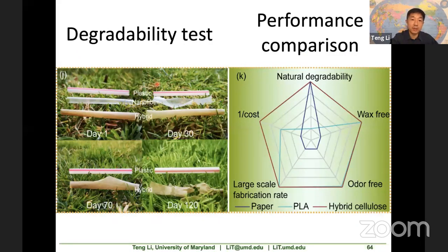We also did the degradation test. On day 120, our straw started to break into pieces. So it definitely is much better than the typical plastic straw. And here is the performance comparison with natural paper and PLA. PLA is a biodegradable plastic. It's actually quite expensive. The material we demonstrated here is overall better than both.